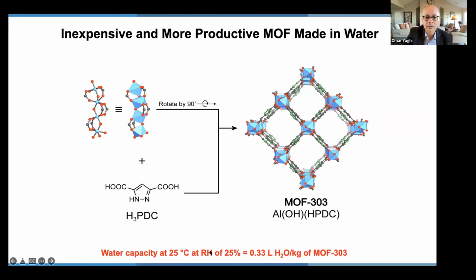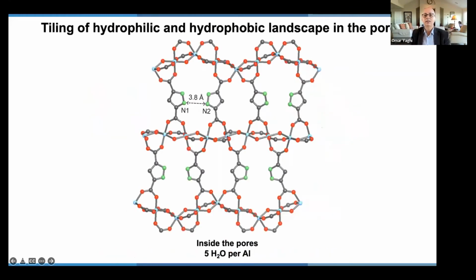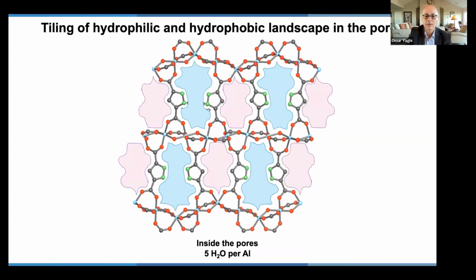And the structure takes up water at very low humidities. I'll show you the isotherm in a second. But the amazing thing about this structure is that if you are a molecule floating inside the pores, this is what you will see. You will see hydrophilic regions and hydrophobic regions. And I'm going to color them. This is the hydrophilic regions, and these are the hydrophobic regions.